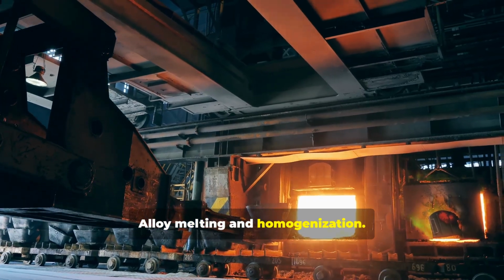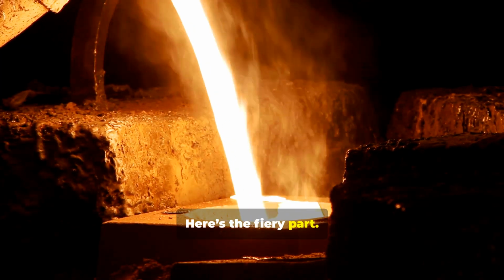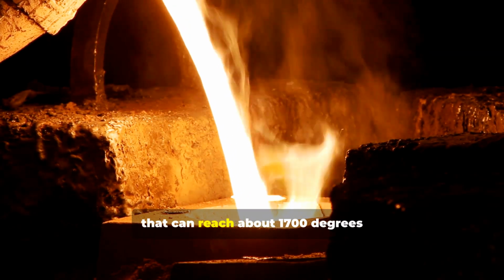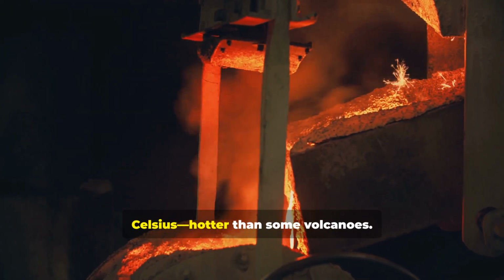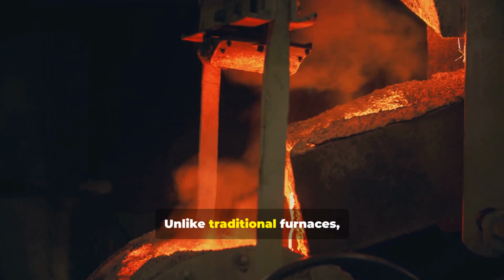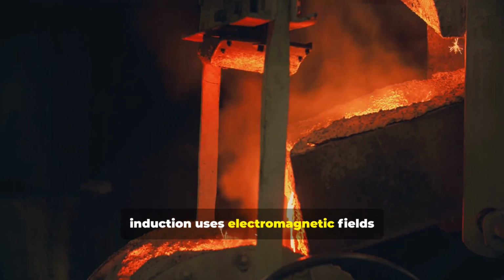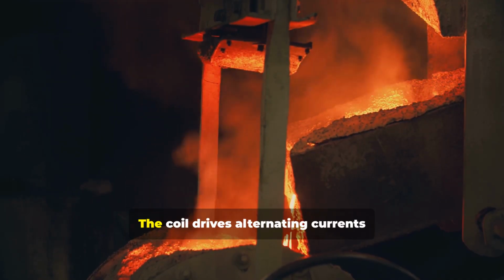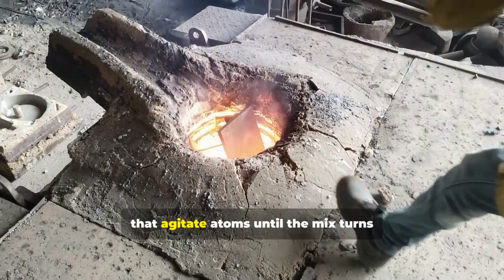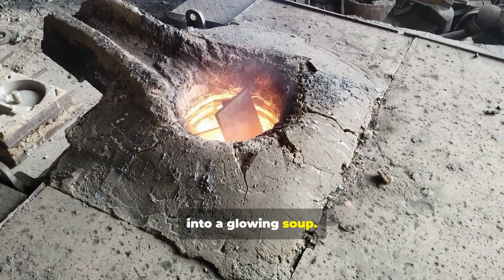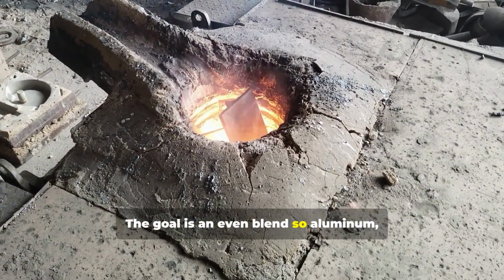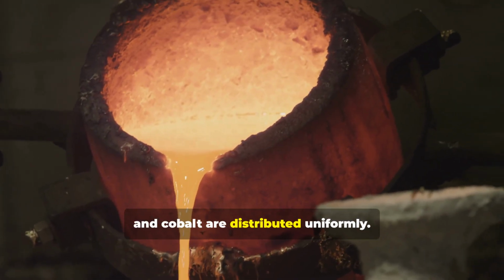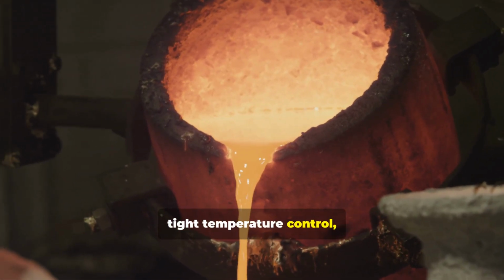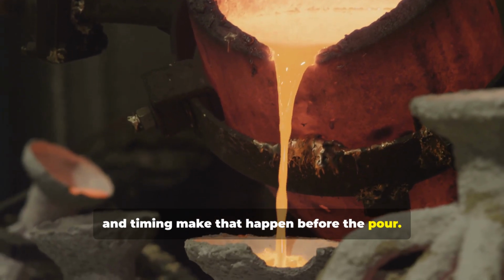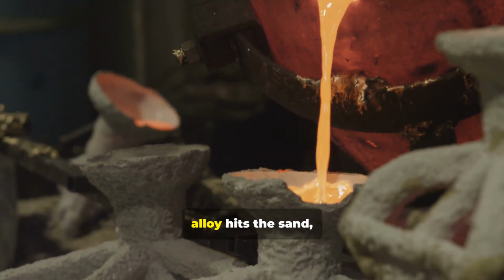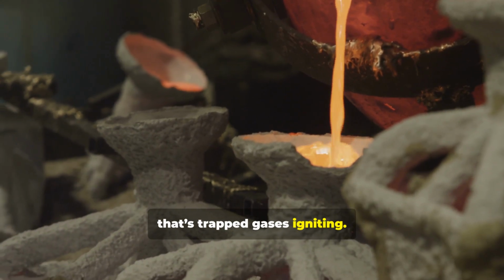Alloy melting and homogenization. Here's the fiery part. Metals go into an induction furnace that can reach about 1700 degrees Celsius, hotter than some volcanoes. Unlike traditional furnaces, induction uses electromagnetic fields to heat the metal from within. The coil drives alternating currents that agitate atoms until the mix turns into a glowing soup. The goal is an even blend, so aluminum, nickel, and cobalt are distributed uniformly. Stirring, tight temperature control, and timing make that happen before the pour. If you see sparks or flames when the alloy hits the sand, that's trapped gases igniting.